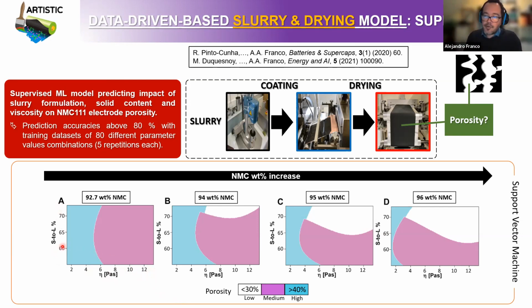You see in this axis the solid content. You see different formulations here. And in colors, you have classes of electrodes corresponding to different degrees of porosity. White means that you have electrodes with porosity lower than 30%, and blue means that you have electrodes with porosities higher than 40%, right? And pink is in between, right? You see that this support vector machine technique predicts that if you use low NMC contents, then it's impossible to get electrodes with low porosity. However, if you increase the amount of NMC in your slurry, it becomes possible to make electrodes with low porosity if you choose the right viscosity value and the right solid content.